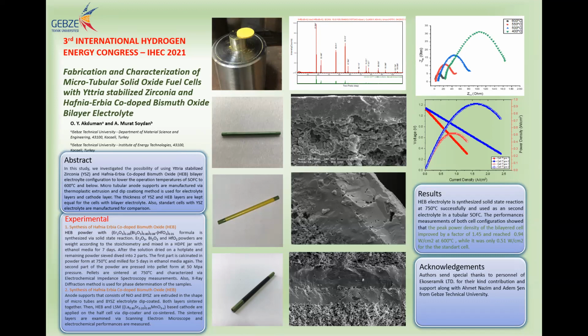We used standard mixing in a polyethylene jar in ethanol media, and after that we dried this and calcined some part of the powder and then pressed the other part of the powder into pellets, and we fired them at 750 Celsius. And then we wanted to see if we have the correct phase.